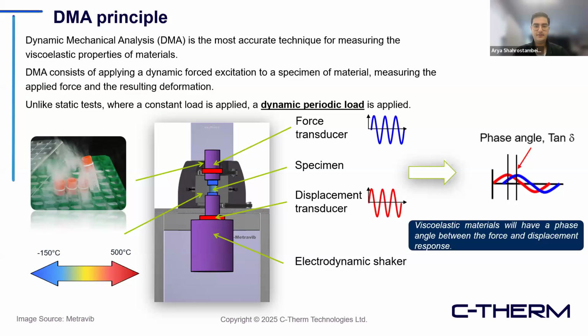So as you can see in this figure, you can see how a DMA works. So basically, this deformation mode is tension. So your specimen is mounted in the sample holder, and it's being deformed with a dynamic periodic load during time. And so Metravib DMA is capable of reaching temperatures as low as minus 150 degrees C all the way up to 500 degrees C, which is a very broad range and definitely suitable for testing cold chain storage materials for different purposes.